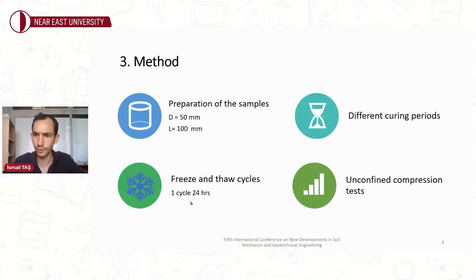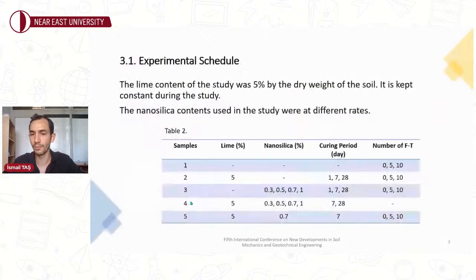The specimens had a diameter of 50 millimeters and a length of 100 millimeters. The temperature for the curing was 23 degrees Celsius. Freezing and thawing temperatures were approximately minus 18 and plus 18 degrees Celsius, respectively. The time for each freezing and thawing action was 12 hours, and so one cycle was completed in 24 hours. The strength of the specimens was determined by unconfined compressive strength tests.